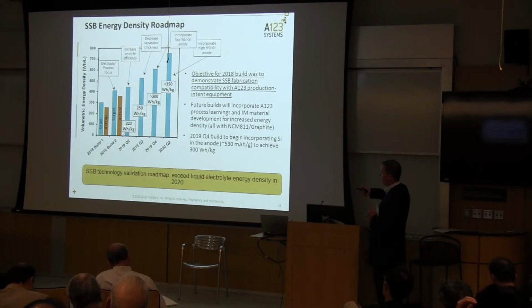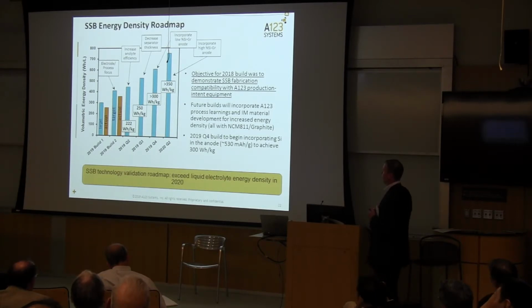I actually just saw the data. This is our goal for the end of June, and the metrics that we are trying to hit in terms of coulombic efficiencies, we achieve them. So we should be able to hit this energy density by the end of June, and I feel confident that we'll march towards 300. This is going to be more of a risk because of the high silicon content. But the point is, in a very short period of time with commercially available active materials, at least on production equipment, we're very quickly reaching over 600 watt-hours per liter and 300 watt-hours per kilogram, utilizing solid-state chemistry.